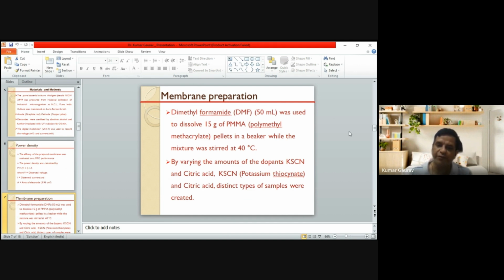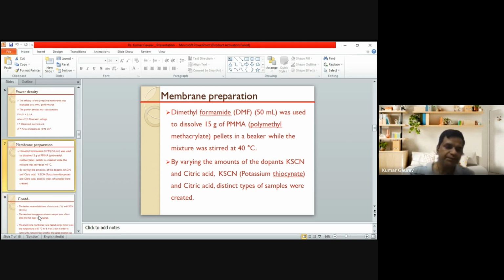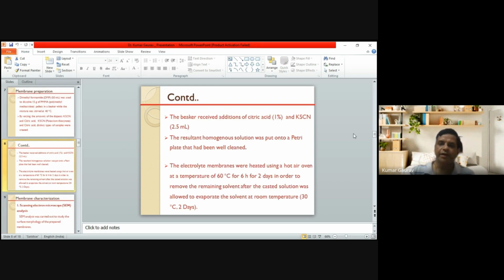For that, we used potassium thiocyanate and citric acid. By changing the concentration of the potassium thiocyanate and the citric acid, we have different types of membrane. But in this presentation I have shown one type of combination. We used the addition of citric acid and potassium thiocyanate, 2.5 ml. After that, we poured the resulting solution into the plate. Then we heated this membrane in a hot air oven at 60 degrees for 6 hours in order to remove different types of solvent, and it can be prepared within 2 days.